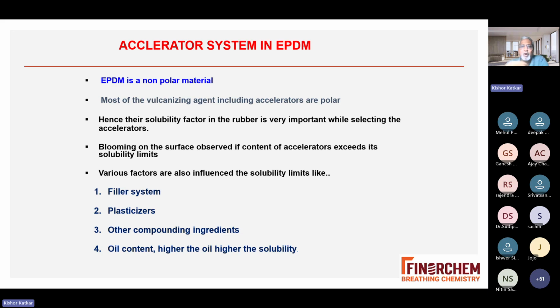Now I have just given a few polymers where special systems are required. EPDM is very critical. EPDM is a non-polar material, and most of the organic chemicals, including accelerators, are polar. Hence, the solubility factor in the rubber is very important while selecting accelerators. Blooming on the surface is observed if the content of an accelerator exceeds its solubility limit. Any material you add to the rubber compound beyond its solubility limit may go into the compound at high temperature, but after curing it will bloom out because the solubility limit has been crossed.